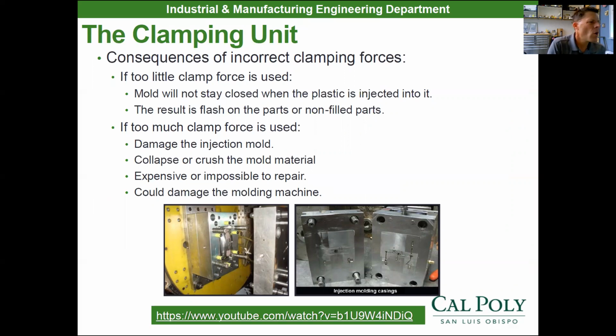Well, if you use too little clamp force, the mold's not going to stay closed when you inject plastic into it. So it'll flash, and that flash won't look good, or you might not fill parts if it opens up because the plastic wasn't able to flow into that cavity. If you use too much clamping force, you can damage the injection mold or crush the mold material and cause a very expensive repair or impossible to repair scenario. Or you could even damage the molding machine if you slam it too fast, too close with too much force. So those are the consequences of improper clamping pressure.